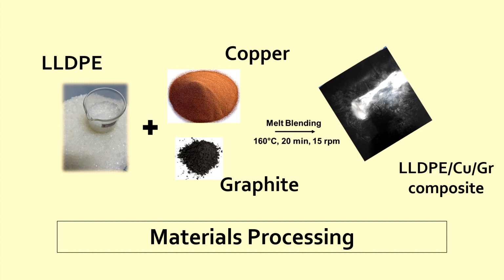In terms of materials processing, we use linear low density polyethylene as the main polymer matrix, combined with copper and graphite, and using melt blending to process the material, which is processed at 160 degrees Celsius for 20 minutes at 15 revolutions per minute using a Z-blade mixer to produce the LLDPE copper graphite conductive polymer composite.